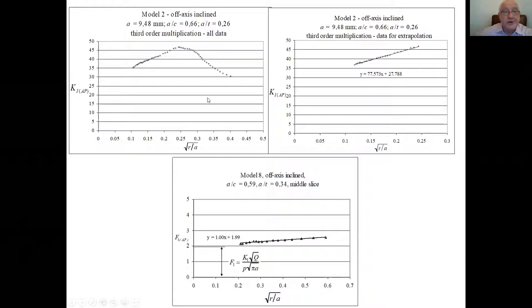Here you have all data which were established for third order multiplication. And of course, you cannot go close to the crack tip. So here in this situation, below r over a of 0.1. And here we had these dimensions of the cracks, the physical dimensions, the ratio between crack depth and crack length of the surface, the inner surface of the tip, and crack length and thickness of the photoelastic model. So of course, out of so many data, and well, if you get so many data, you can be happy. Of course, you can choose what would be useful for extrapolation. So being in the K-dominance region, extrapolate this towards the tip of the crack and establish K1.